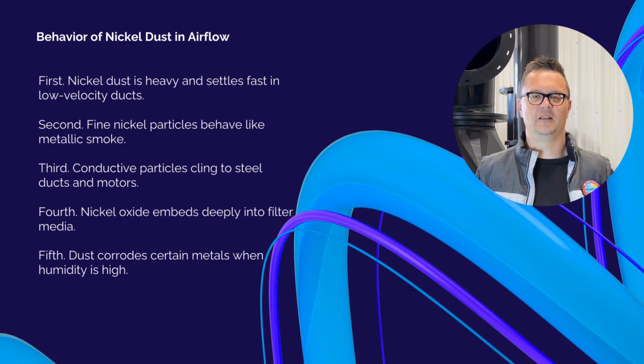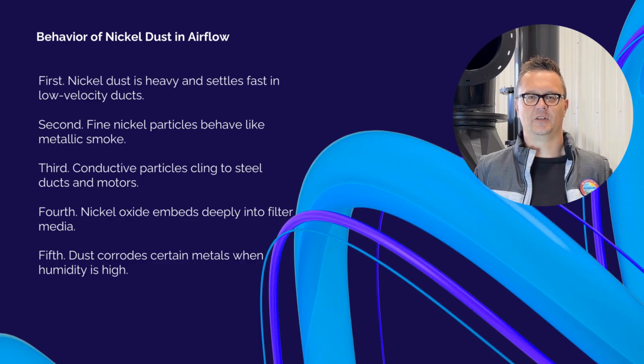Behavior of nickel dust and airflow. From an engineering perspective, first, nickel dust is heavy and settles fast in low-velocity ducts. Second, fine nickel particles behave like metallic smoke. Third, conductive particles cling to steel ducts and motors. Fourth, nickel oxide embeds deeply into filter media. Fifth, dust corrodes certain metals when humidity is high. For nickel dust, I designed duct velocities from 4,500 to 6,000 feet per minute.